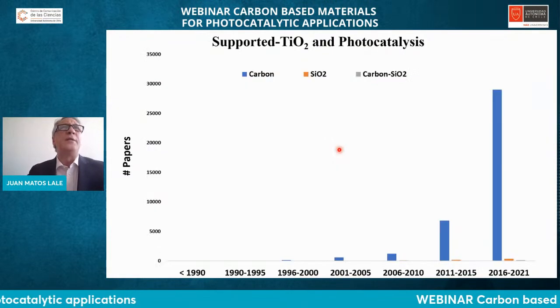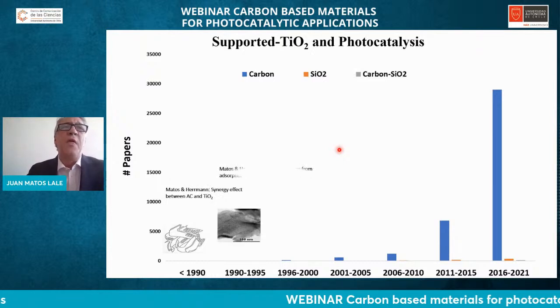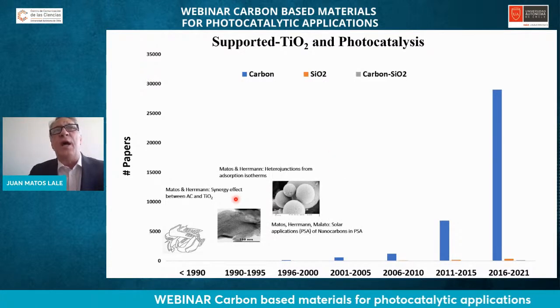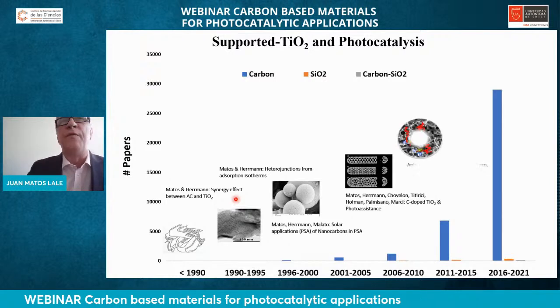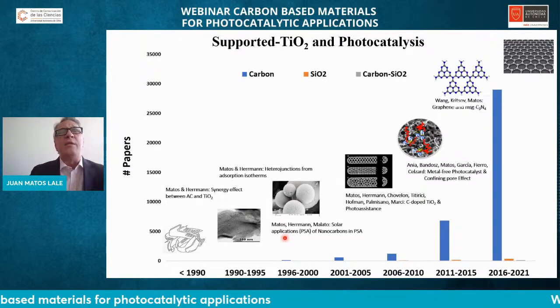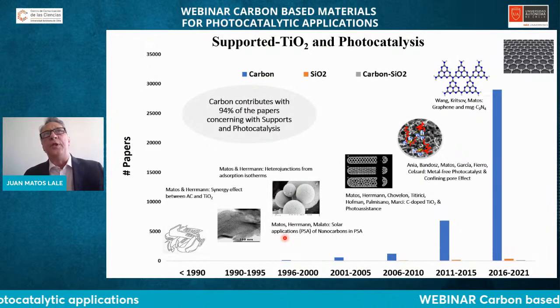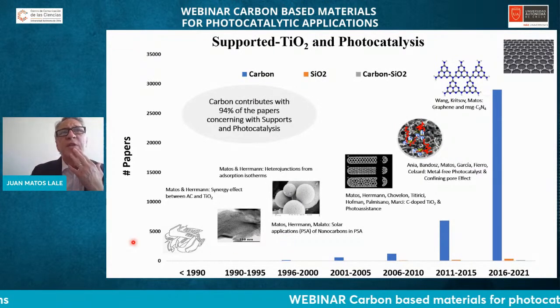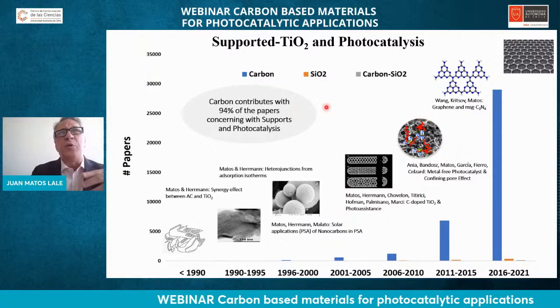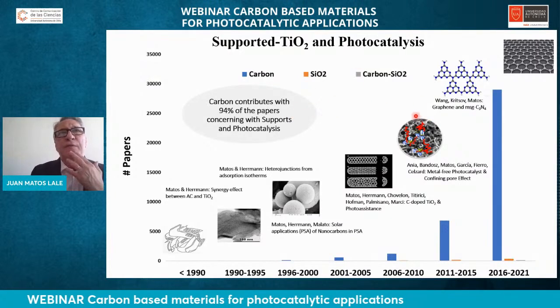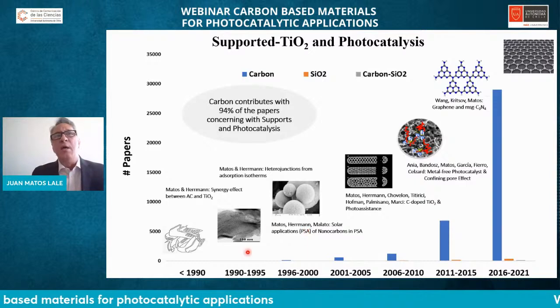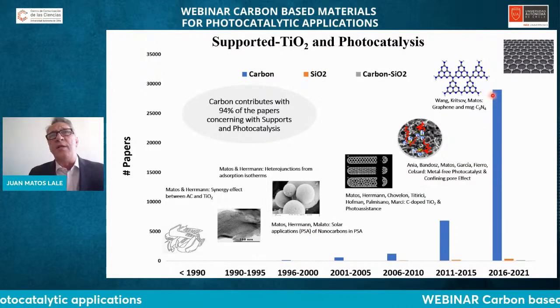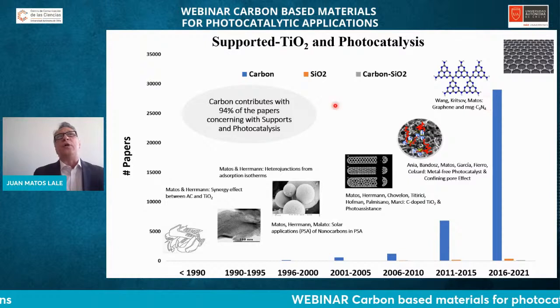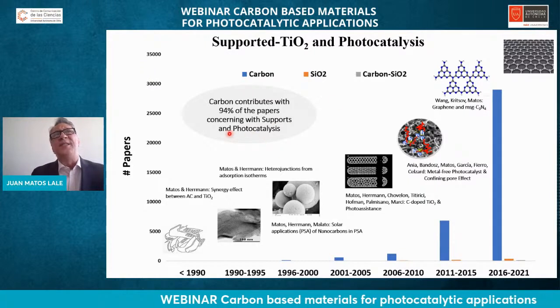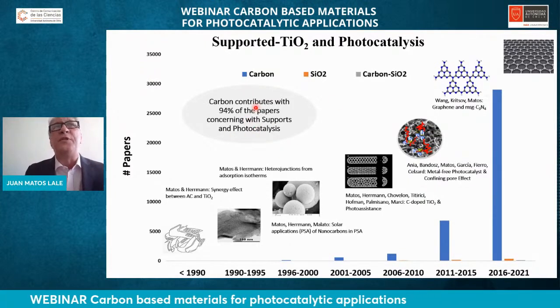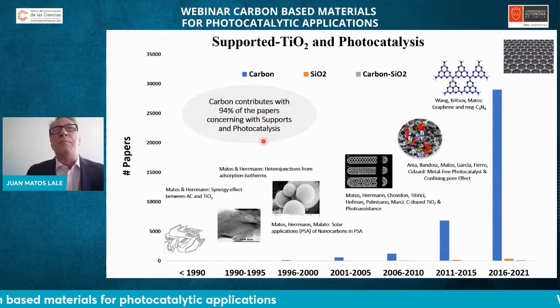But several groups suspected this 30 years ago, and we started to work with a combination of materials. We started a line that we call carbon-supported photocatalysts. We have dealt with different kinds of carbon-based materials, but also with silicas or combinations of nanoporous carbons with silica. But by far, carbon material is the best support used in photocatalysis. More or less 94% of all the papers concerning supports in photocatalysis deal with carbon materials.